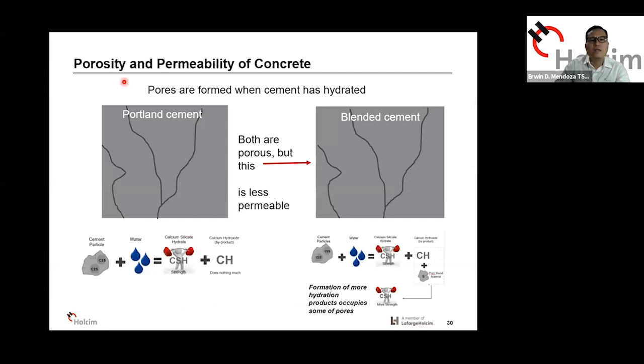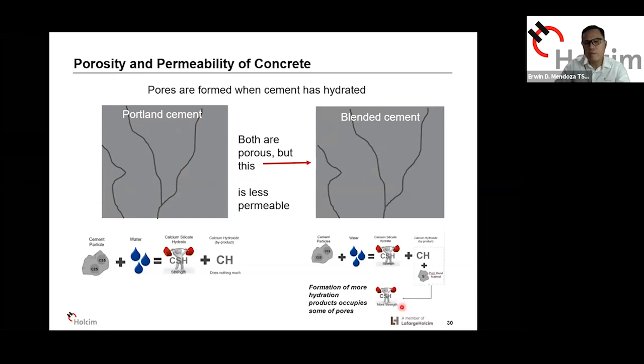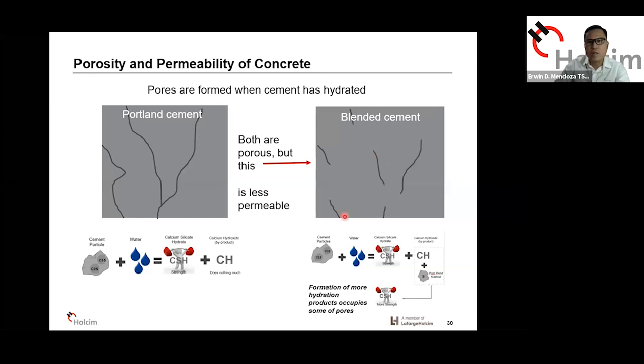Porosity and permeability of concrete — are they the same? Portland cement forms capillary pores when it starts to hydrate. For blended cement, the same pores form, but over time, because of the additional reaction, more hydration products are formed that fill up the pores. This creates discontinuous pores — Hindi siya tuloy-tuloy — making the concrete less permeable. Both are porous, but one is more permeable. That's because of the additional hydration products that happen when you use blended cement, which also creates more discontinuous pores.